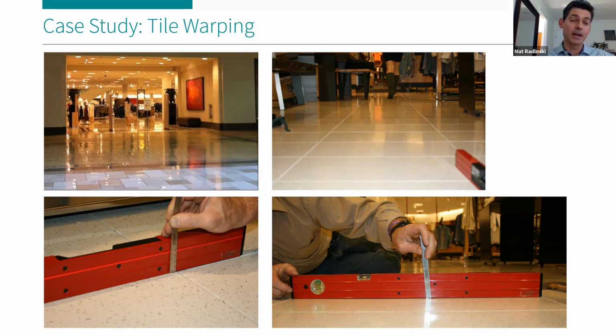In this case, there was no cracking in the tile. That's the good news. But the individual tiles were warping in the opposite direction to what I described in the example before. So the edges of individual tiles were lifted as opposed to the centers. The centers, in this case, remain bonded to the substrate. The edges were not, and it created a fairly unsightly appearance, especially given the location and the fact that it was a brand new remodel project.